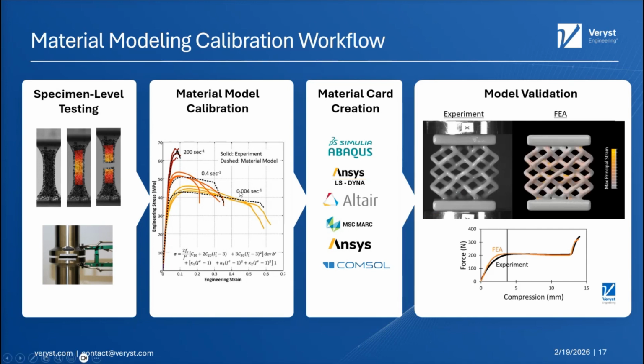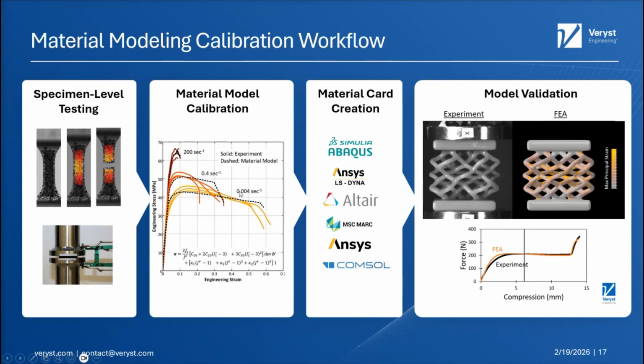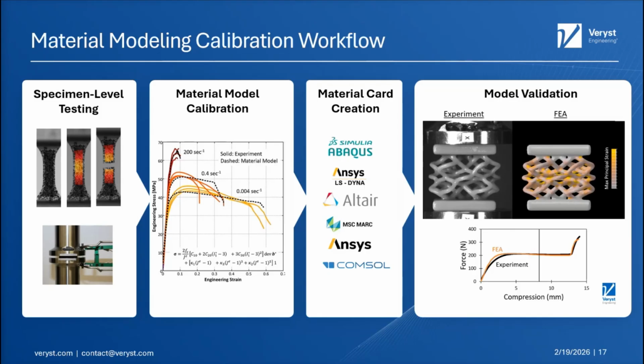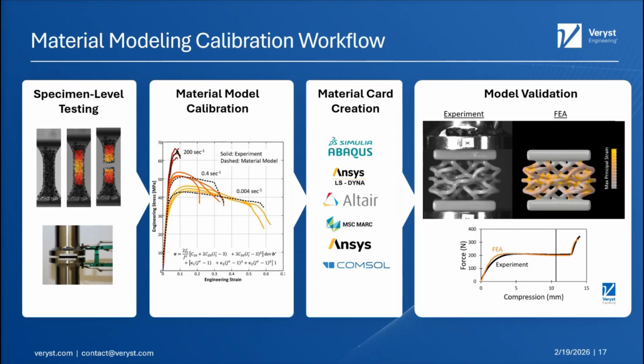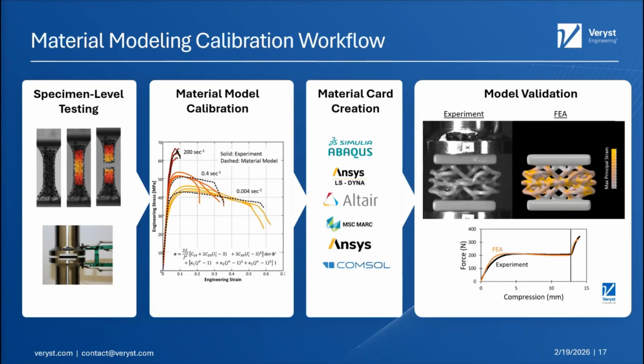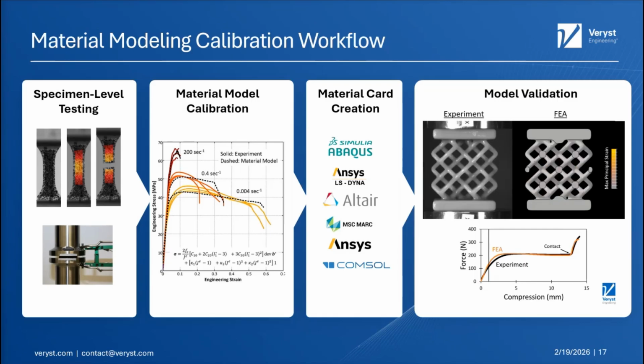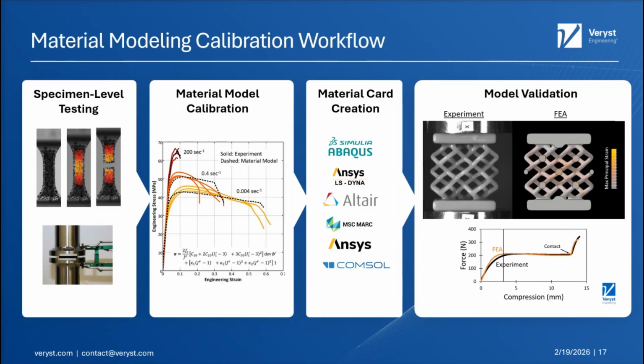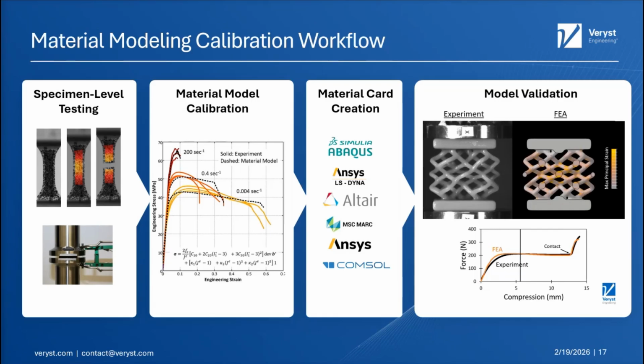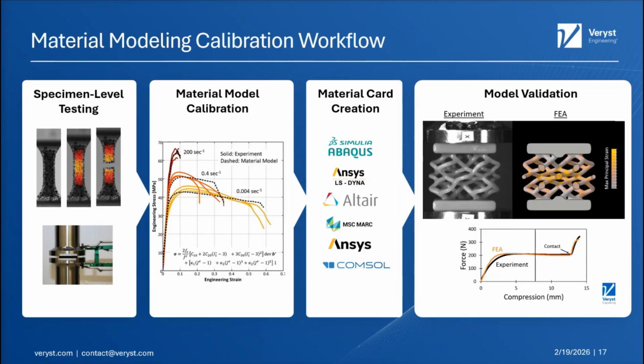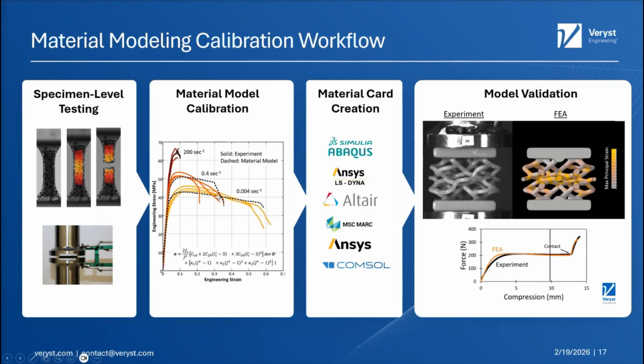The next is the results that we get from that. You can see some tensile tests in the solid lines on a rate-dependent thermoplastic material, and the dashed lines are the material model that we calibrated. We chose some equations and chose the parameters to match that well, and you can see that we're capturing the rate dependence of this material.